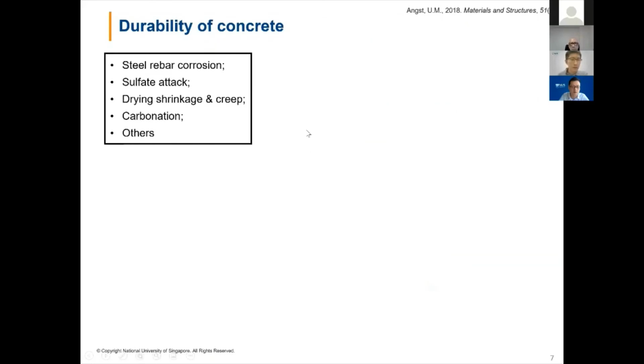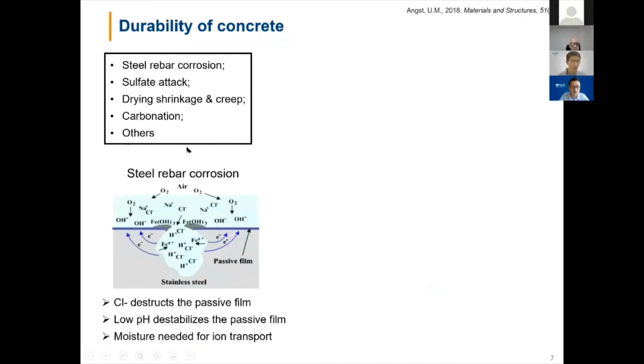Now, moving on to the durability of concrete, the research community has long-term interest in a list of phenomena that cause the degradation of concrete. For example, steel rebar corrosion, sulfate attack, drying shrinkage and creep, carbonation, and many other phenomena. To give you an example, for steel rebar corrosion, we already know that when we place steel rebar in concrete, the surface of the steel rebar will be covered with a thin film. We call it a passive film. This film is very dense. It prevents the steel from corroding.